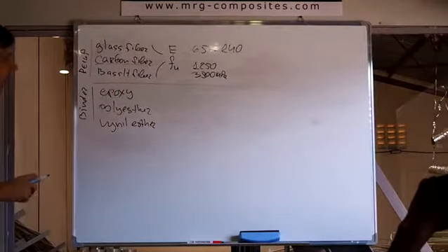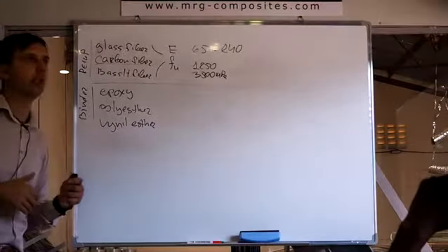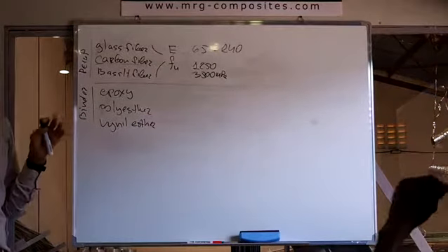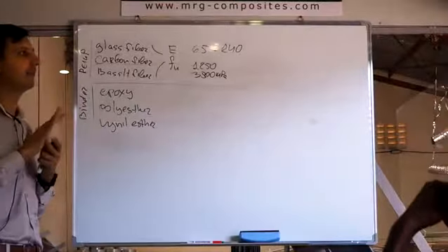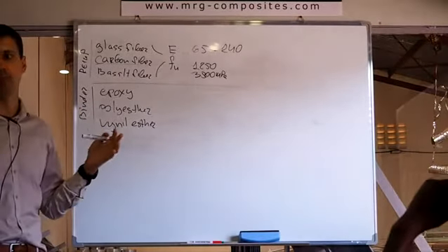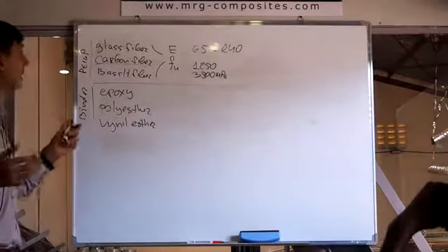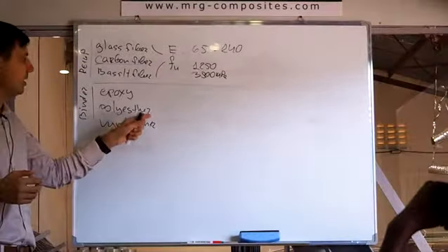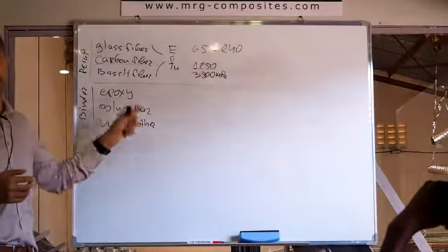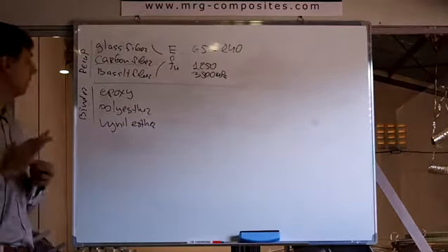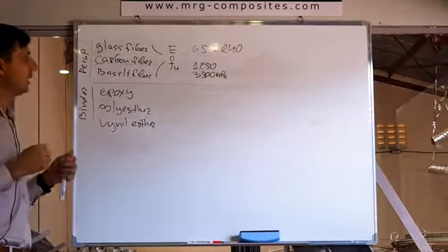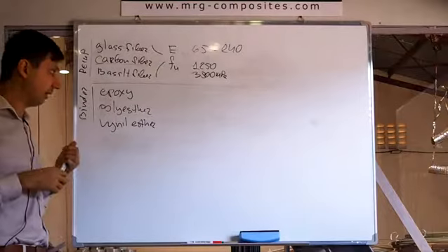What is the difference between them? Actually, the difference is really huge. Most of the time, when you see composite products, let's say some bumpers, some covers, something like this, on borders or something, it's made of glass fiber and polyester resin, because polyester resin is minimum 3 times cheaper than epoxy, and much cheaper than vinyl ester resin. And I can give you an example.